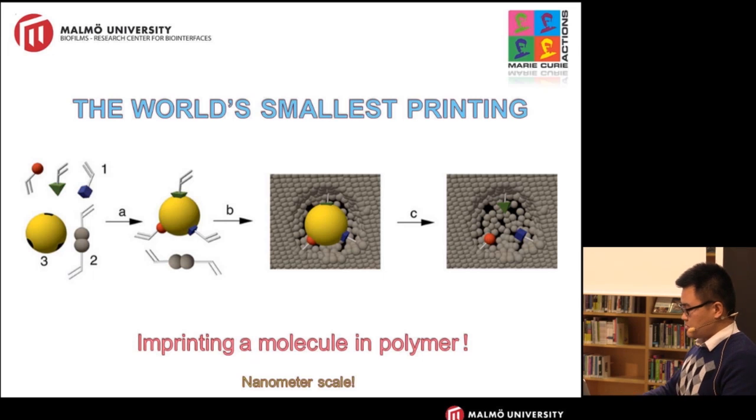So I can say some things in detail about how to prepare this. To prepare the molecular imprinting matrix or polymers, if you want to imprint molecules, for example, this is a real chemical structure, and then the cartoon. We need the monomers. Then these monomers can interact with these molecules, and they can capture them using different bonds, maybe chemical bond, hydrogen bond, or hydrophobic interactions.